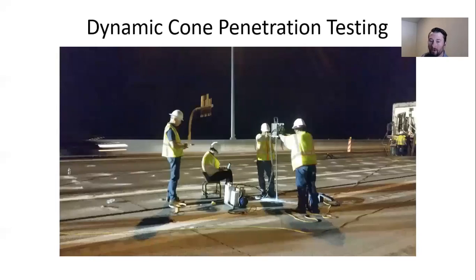In this case, we were going so deep that the handheld drills that we use, the handheld hammer drills that we use to pilot holes for the injection pipes, as well as drive the injection pipes to depth, it wasn't enough. We were building so much skin friction on the injection pipes themselves that even if you could pilot a hole to 15 feet, you couldn't push the half-inch pipe through it. And so we were having to go with larger diameter holes. We ended up using a percussion drill mounted on the boom of a full-size excavator. I'll get to that here in a second, but I'll kind of step back to the dynamic cone penetrometer.